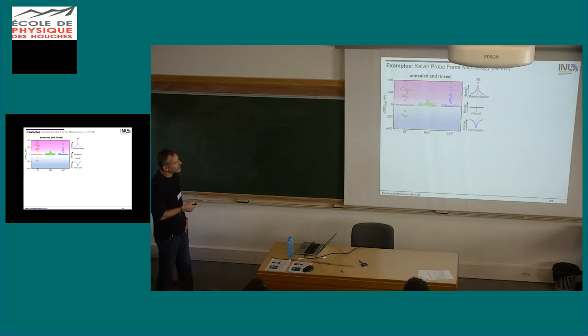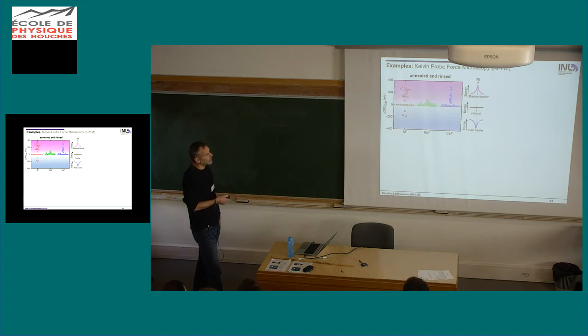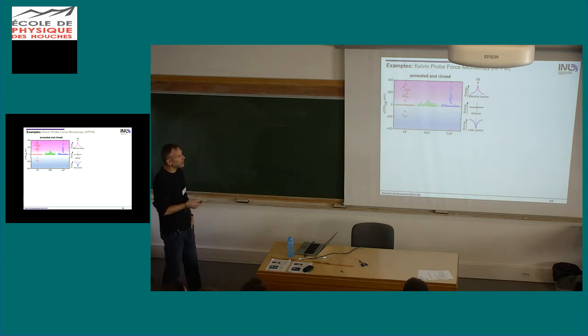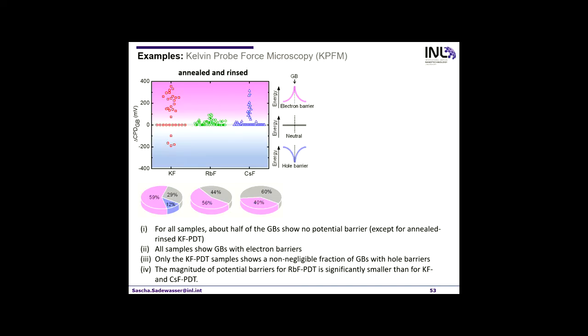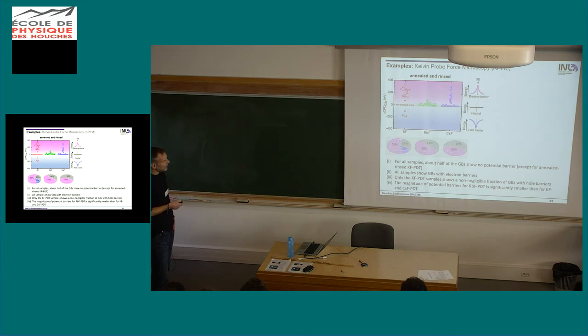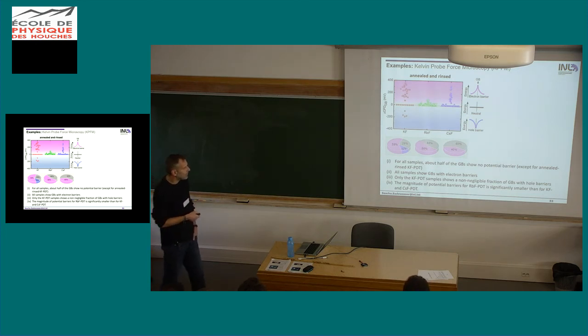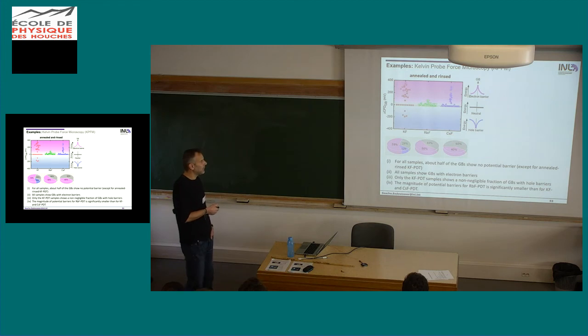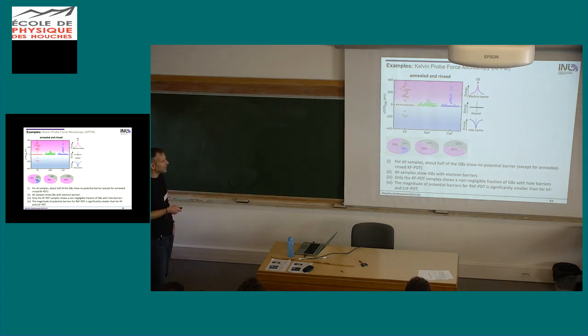So what we know, of course, is here we have a higher work function at the grain boundary, so this corresponds to an electron barrier. So if I have a transport across the grain boundary, this would be a barrier for electron transport. Neutral one doesn't change anything. And for the downward one, we have a hole barrier. So now we talk more about electron and hole barriers in this case. So we statistically analyze this, and we see we have here about half of the grain boundaries in all 3 alkali treatments are electron barriers. Here we have some hole barriers, and then we have also a fairly large fraction of neutral ones. So more or less 50-50 here, and here we have a couple of 10%, 12% of hole barriers.